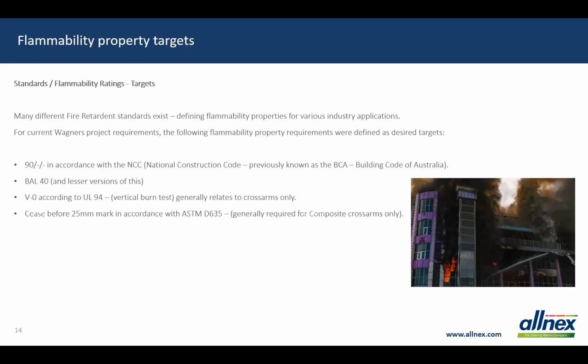Now, for this project, the set of desired flammability properties of the cured vinyl ester composite was defined by these standards. And so these are the desired flammability ratings, if you like, to the different codes and standards that are relevant for this work. We are focusing on UL94 as far as screening properties initially in the lab, trying to achieve an approximate V0 rating. It's the highest one possible there. It's a simple self-extinguishing test, which I'll explain in a minute.